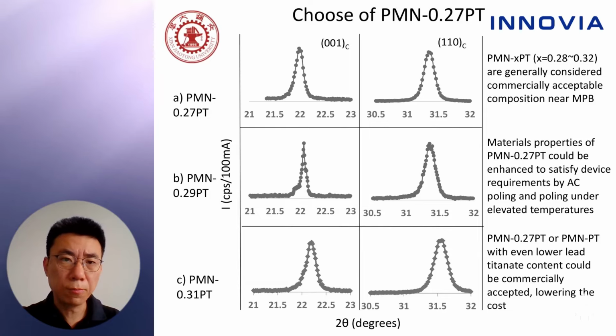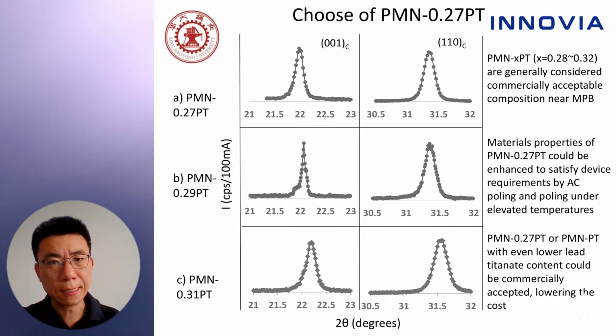We take the crystals, grind them into powders, put them under diffraction, and see that with the increase in the degree of the peaks, the higher the composition, the higher the 001 peaks and 110 peaks, which is consistent with the theory.